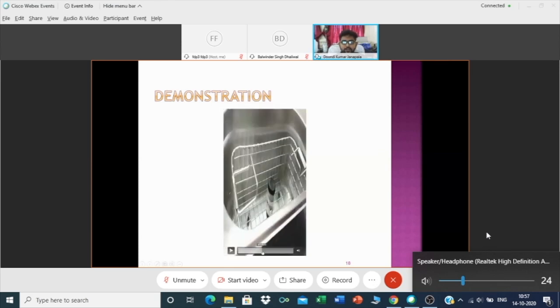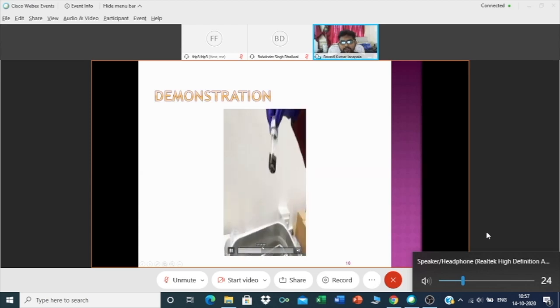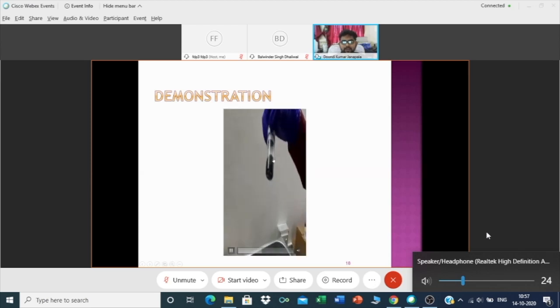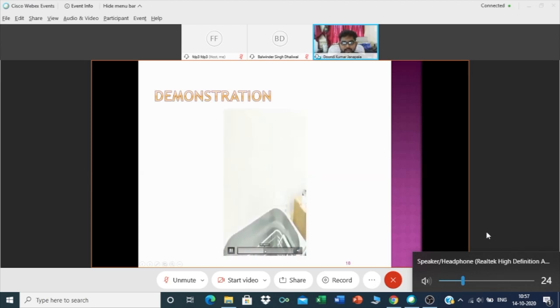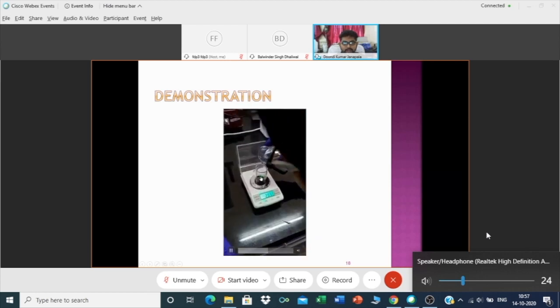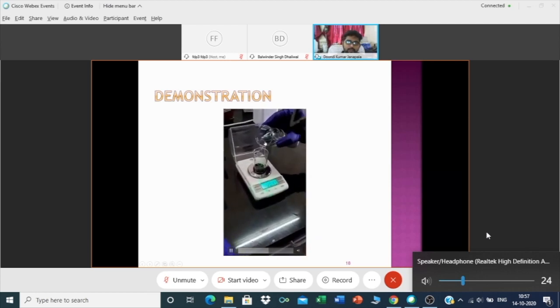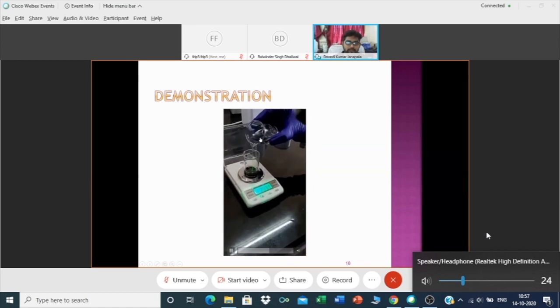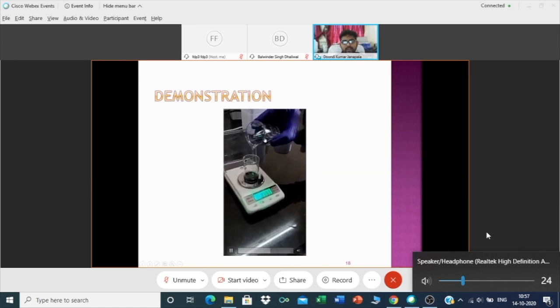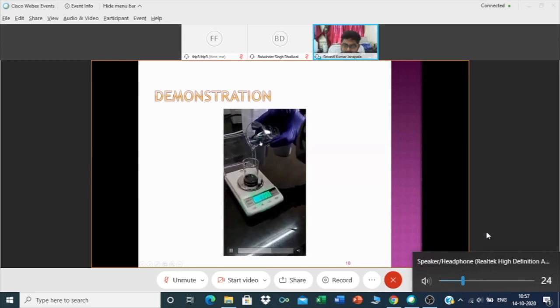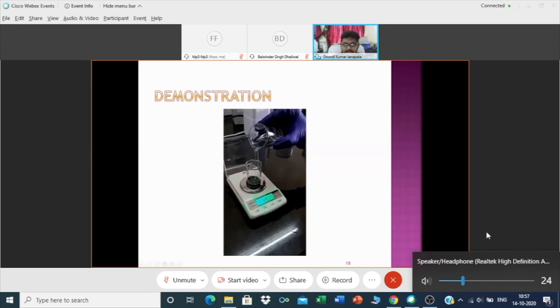Once you do it properly for around 20 minutes and your mixture is very uniform, you put it in your beaker, and then you pour in the PDMS which you processed to remove the bubbles. I took 2 grams of this solution and around 7 grams of polymer, which is mixed with base and curing agent, with the bubbles removed by degassing and everything, and I added that.